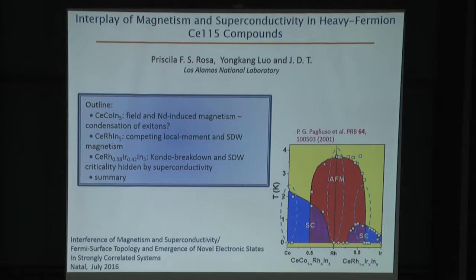And then finally, we'll come to a compound that has both rhodium and iridium, and in this particular compound, there is magnetism coexisting with superconductivity. And what we can do is apply a magnetic field to this material and suppress its superconductivity, in which case we find evidence for two completely different types of quantum criticality, so-called Kondo breakdown and spin density wave criticality. Both of these criticalities are hidden by the dome of superconductivity in the absence of a magnetic field, but this discovery allows us to connect in some way all the cerium-115s that are shown in this phase diagram, their superconductivity, to quantum criticality.